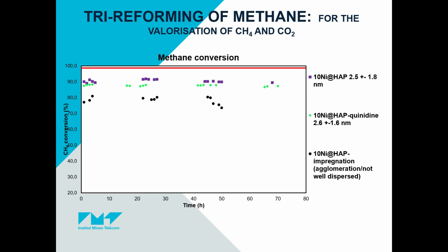So far, hydroxyapatite-based catalyst prepared by this new strategy has been tested and compared with the nickel-based catalyst prepared by the impregnation method. One of the most commonly used methods for preparing this catalyst, in which it's difficult to control the particle size and homogeneity of our active site.